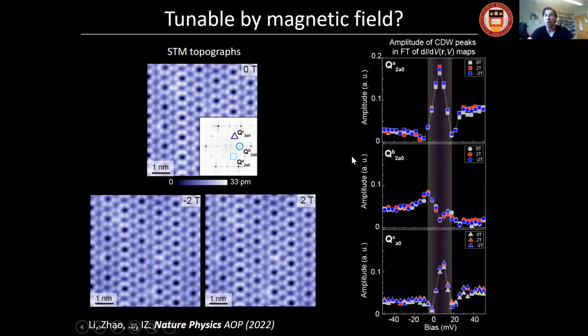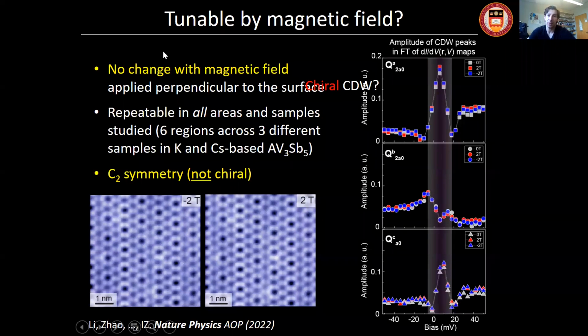We take DOS maps as well, then plot the CDW amplitude as a function of field. Each panel represents a different CDW direction. This is QA, this is QB, this is QC. The x-axis is energy again, the y-axis is the amplitude. Different colors represent different magnetic fields. What you're going to see is there's very little, within our resolution almost no difference between different fields along different directions. So what we see is no change with magnetic field when we apply it perpendicular to the surface.